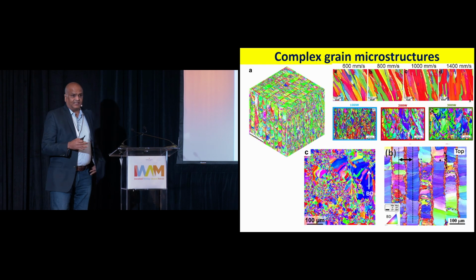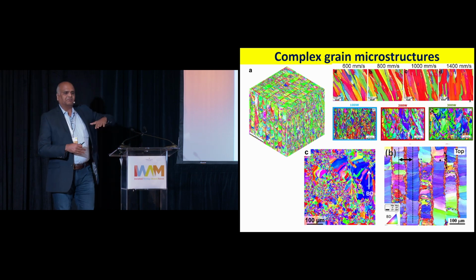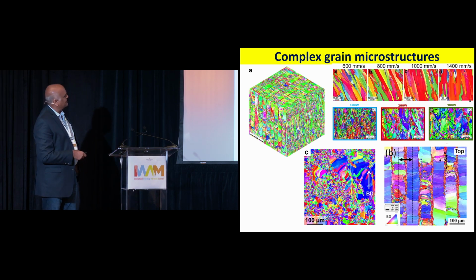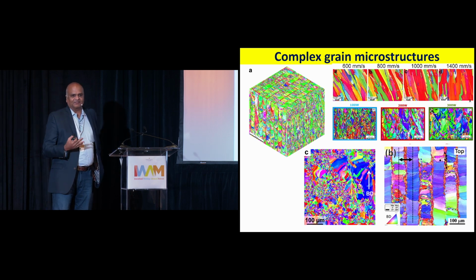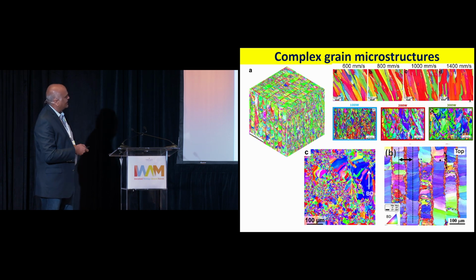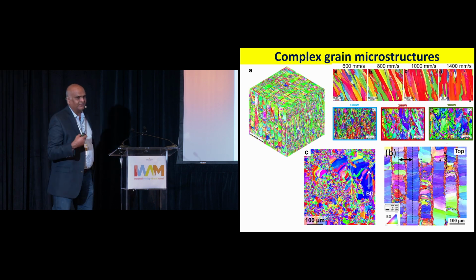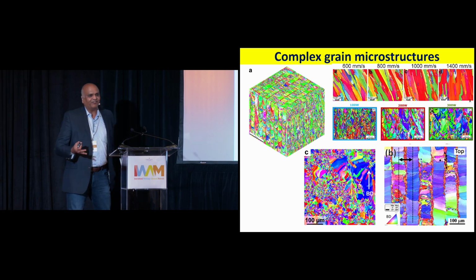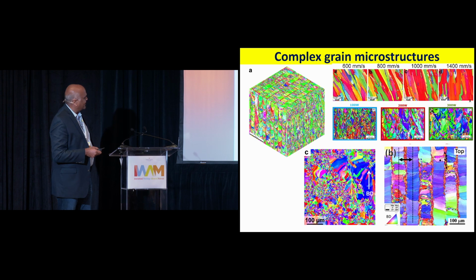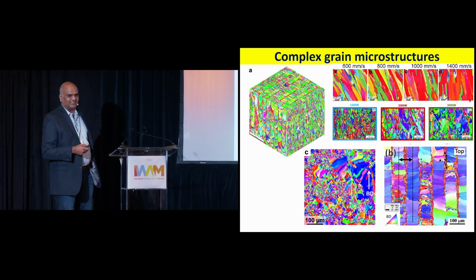Now that's about the cell structure. If you zoom out to a slightly larger scale, you see very complex microstructures. These are very difficult to understand. I think I showed you a structure like this earlier. Depending on your scanning rate, the grains tilt more into a vertical direction, depending on the power you use. These are not easy microstructures to interpret, even for metallurgists well versed with this. You can see structures where the grains seem completely inhomogeneous.